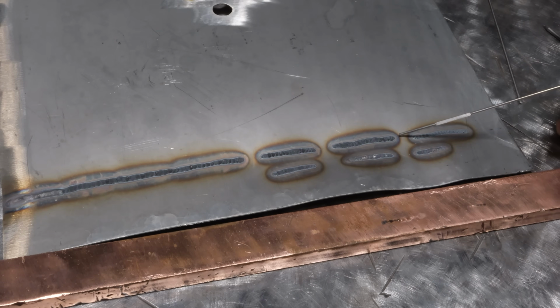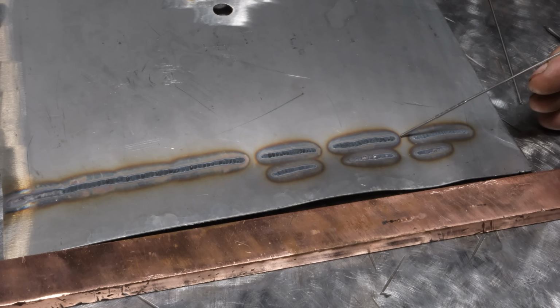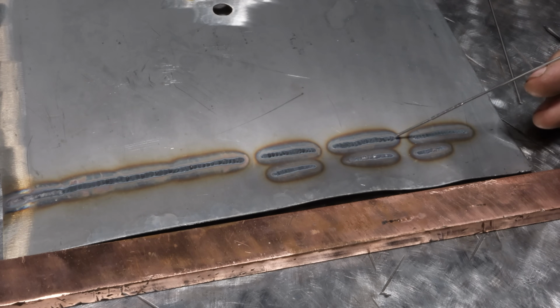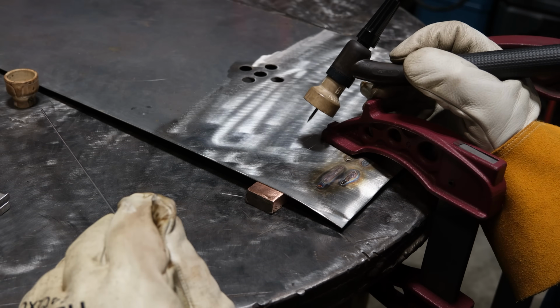If you're building stainless steel car headers or turbo manifolds, having this crap on the inside of the pipe is not good. As that pipe experiences thermal changes from being super hot to cold, along with all that vibration, this is a great place for cracks to start and propagate from. In my experience, for thin wall tube that's used to make turbo headers, you will have weld failures and cracks if this is what the inside of your weld looks like. So again, it's all in what the use the weld is going to see as to whether or not this is acceptable. So now I'm going to take what we learned so far.